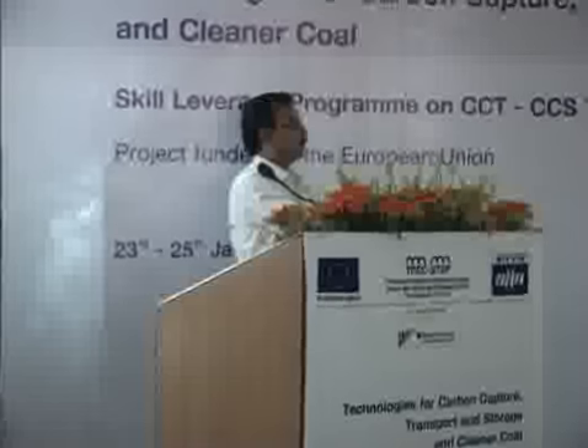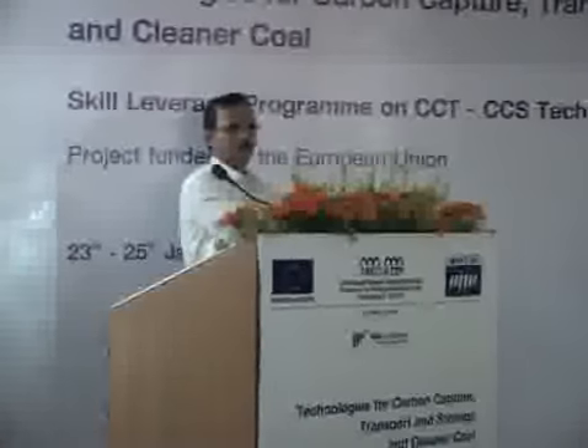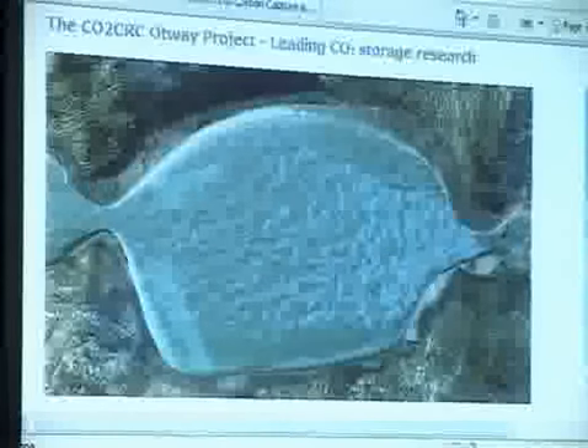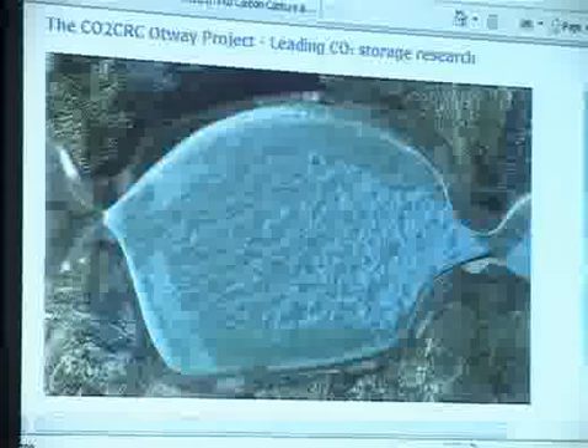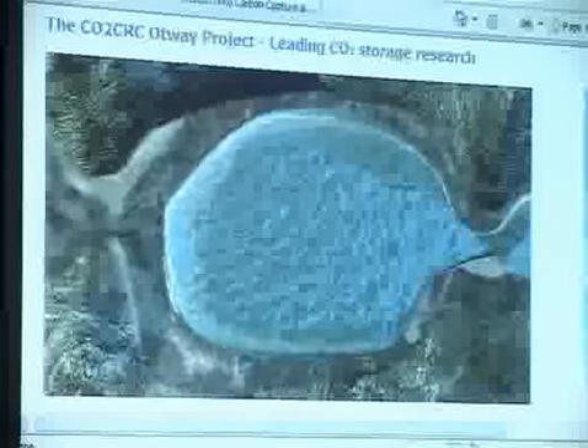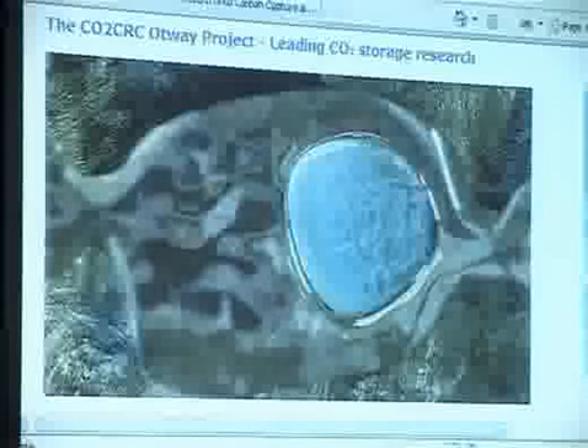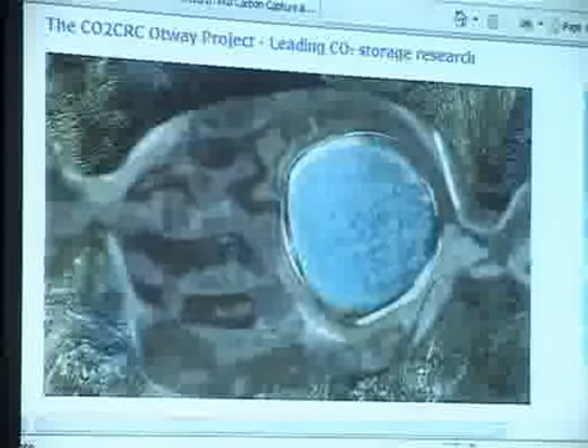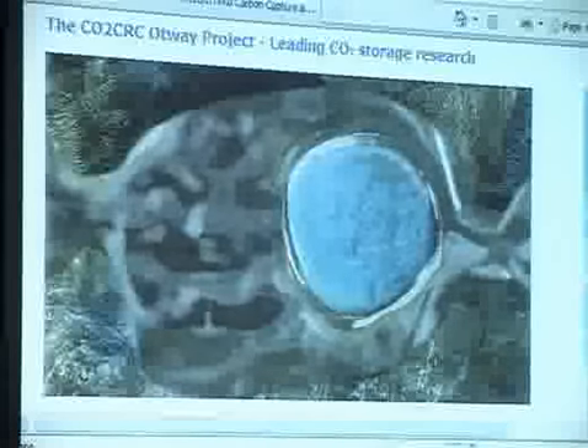Stage 2 is about demonstrating residual trapping. Residual trapping occurs when a small amount of CO2 becomes disconnected or snaps off from the stored CO2 as it moves through the porous rock. Tiny bubbles of CO2 are stored in the pores, trapped by surface tension. The CO2 can't move out of the pore space and remains fixed underground.